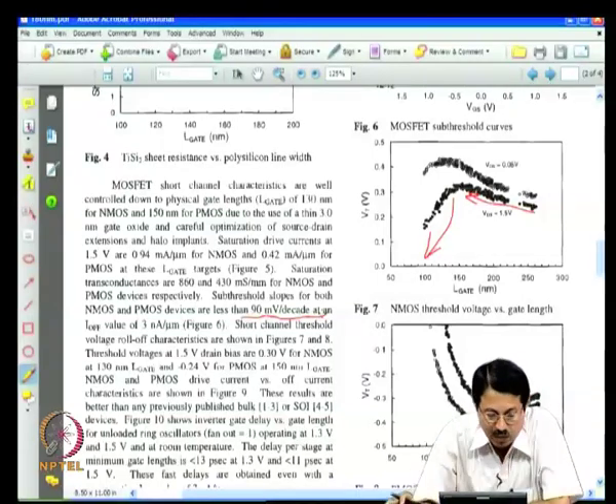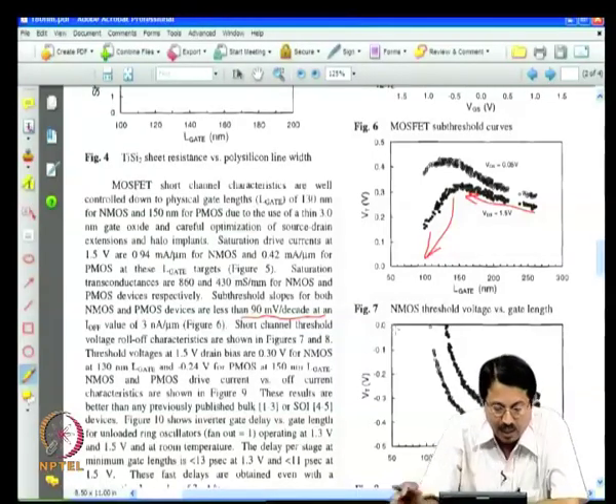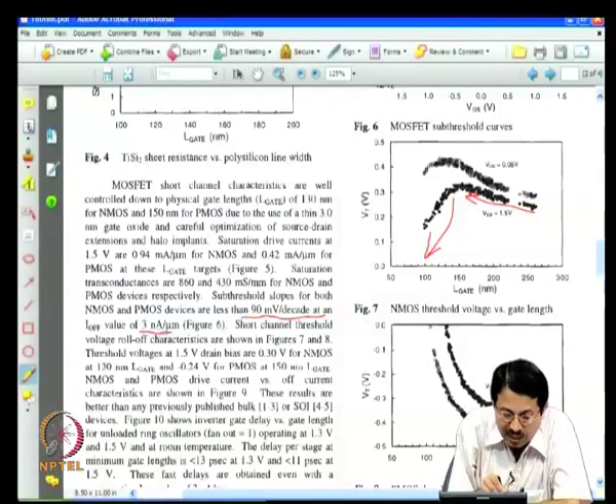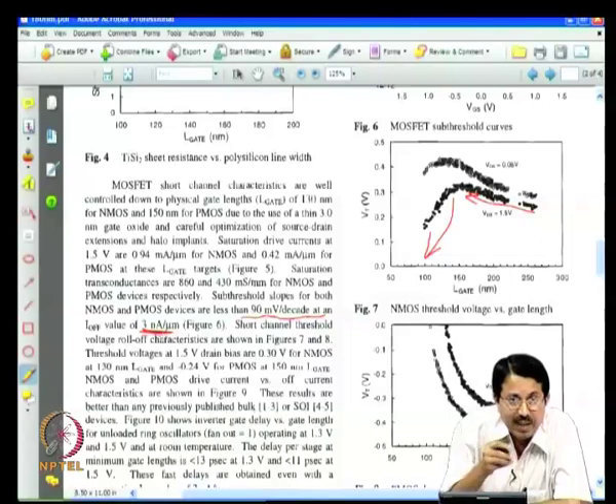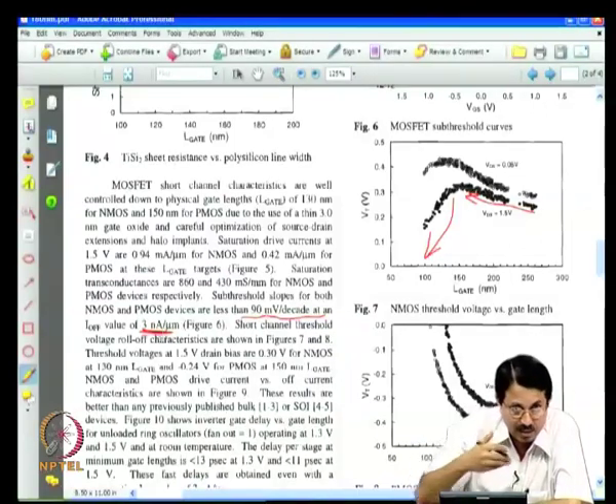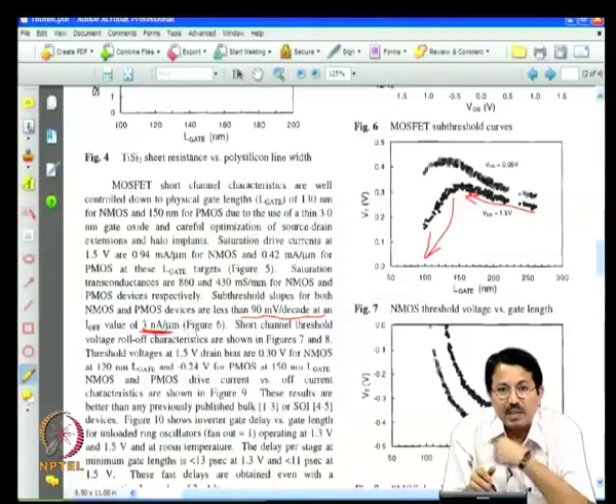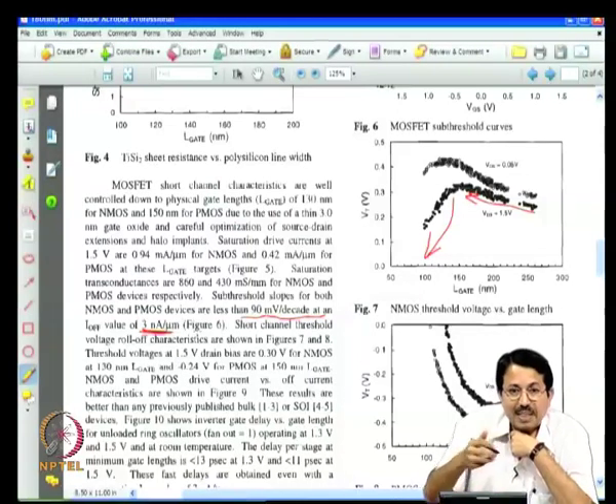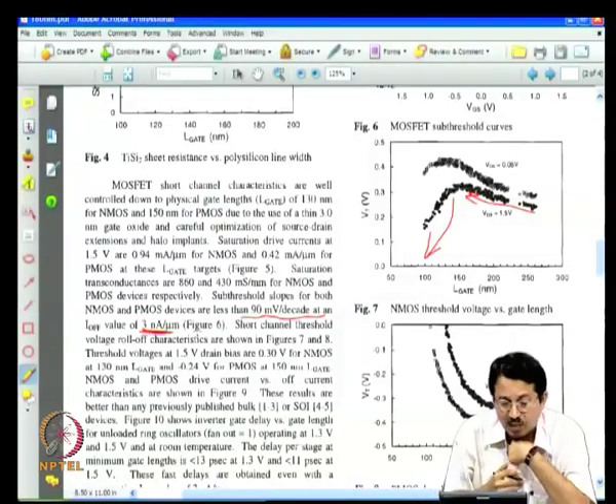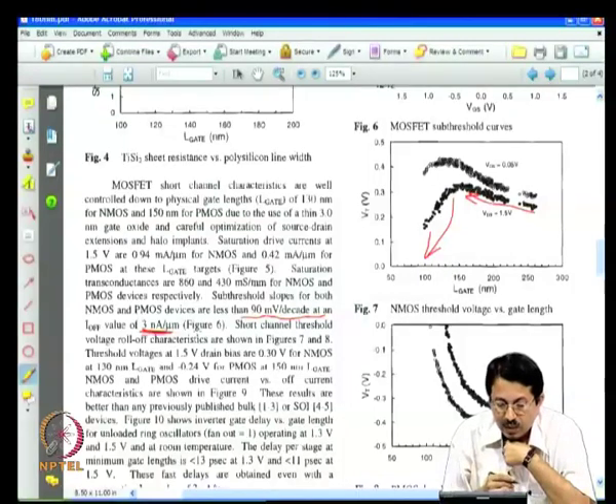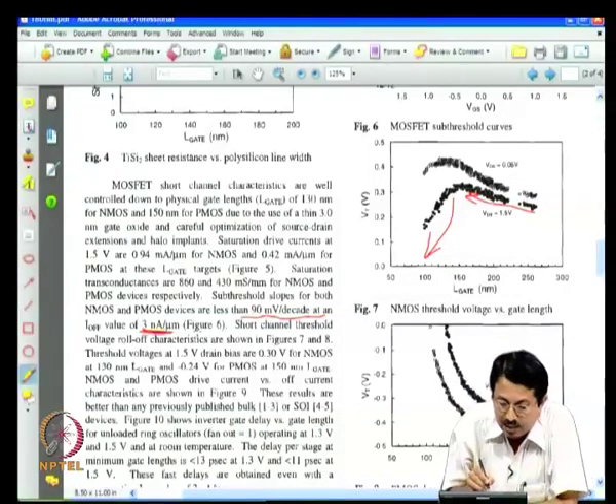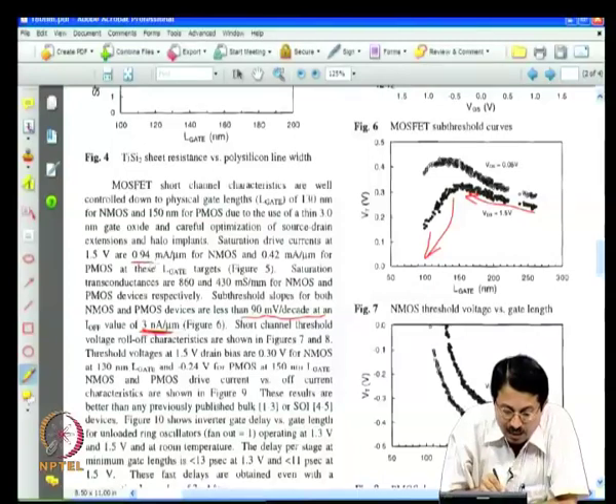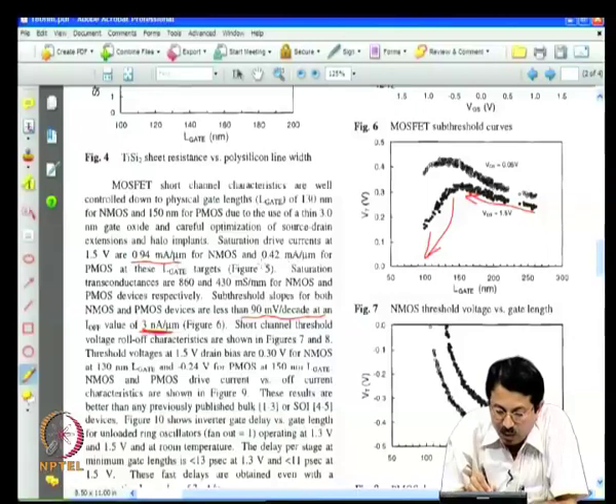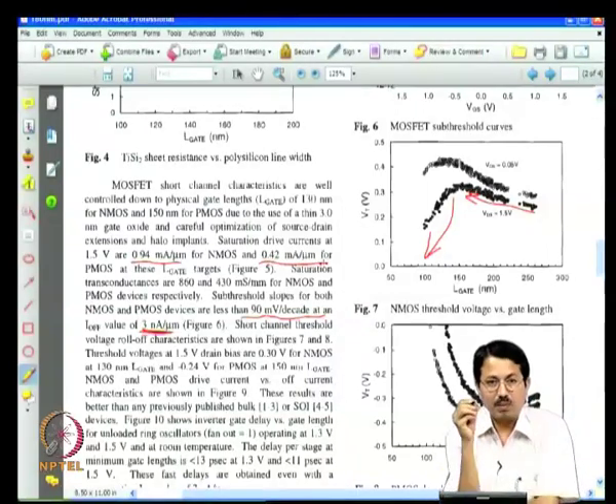So, they have been able to achieve 90 millivolt per decade, and their off currents are of the order of 3 nanoampere per micrometer. We always specify off current in terms of ampere per unit width. Depending on how many microns your transistor width is, you multiply that, you get the off state current. And your on state saturation drive currents are 0.94 milliampere for NMOS and 0.42 milliampere for PMOS.